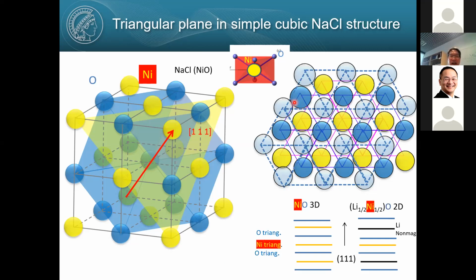Okay. And maybe instead of sodium chloride, let me say magnetic nickel and non-magnetic oxygen, nickel oxide. Okay, yellow nickel, blue oxygen, right? So you have first an oxygen triangular layer, and the next one is a nickel triangular layer, and below is again an oxygen triangular layer. Okay, so therefore nickel is magnetic, and you have a triangular lattice of nickel here, sandwiched by triangular layers of oxygen. And you can see this nickel is coordinated with 6 oxygen, forming an octahedron like this. Okay, so you have a triangular lattice made of nickel oxygen 6 octahedra. As I said, it's a piling up of triangular nickel lattice and oxygen lattice. Okay, but it's still 3D.